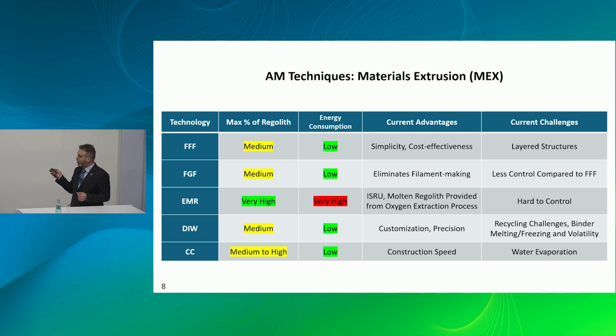Current advantages for FFF include simplicity and cost effectiveness, but it gives us a layered structure. FGF eliminates the filament making step, which is very important for the lunar surface to keep it simpler. But it offers less control compared to FFF. EMR is 100% ISRU based, and the molten regolith can be provided from oxygen extraction processes, but it's hard to control. That's the downside. DIW offers high customization ability and high precision, but again, we have recycling and binder related challenges. And for contour crafting, construction speed is very high, and water evaporation is the main challenge.